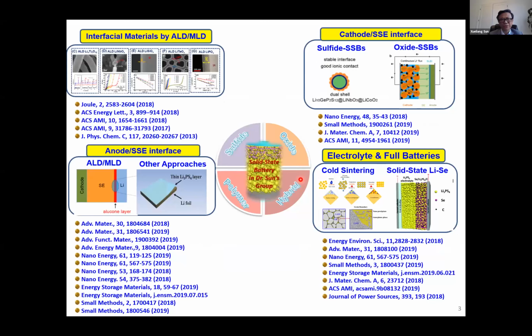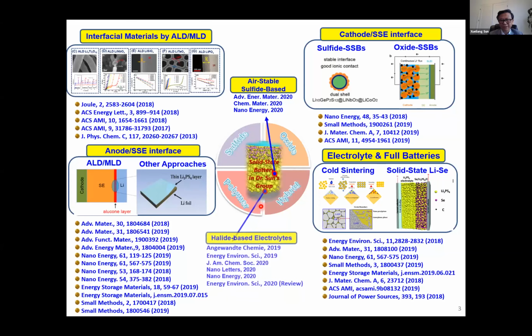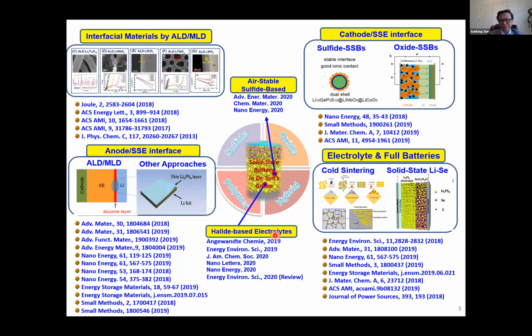So here our group works on different systems of solid-state batteries. For example, polymer-based, sulfide-based, oxide-based, and hybrid. We focus on the interface control, particularly using, for example, atomic layer deposition and molecular layer deposition to control the interface. For example, with the anode, lithium metal, or the cathode, or even the solid-state battery electrode. We also synthesize solid-state electrolytes like air-stable sulfide-based electrolytes. And we also work on another type, halide-based electrolytes. So today I will give a two-part example. One is using the sulfide-based electrolyte, talking about the interface with the cathode. And I'll give another example of halide-based electrolyte.